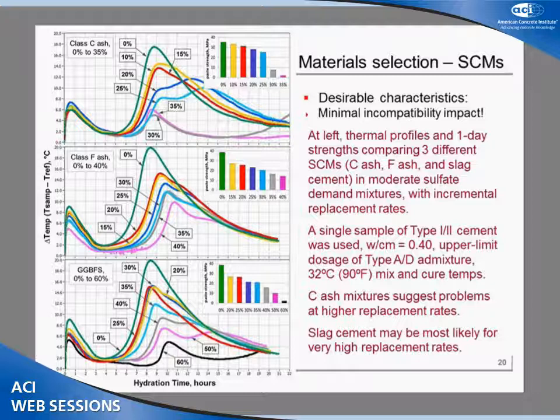Let's start with looking at the F ash. This is a very low calcium, pure pozzolan Class F fly ash. And as you go from no replacement at all in the case of the green curve to up to 40% down here, what's really happening is pretty much just dilution of the OPC in the performance that's associated with that. You can see the equivalent effects on one-day strength. Very little potential incompatibility of material influences from this particular source of Class F fly ash. The slag cement down here on the bottom, slag cement's up to 50% or so common in concrete. It's really not much of a challenge most of the time.